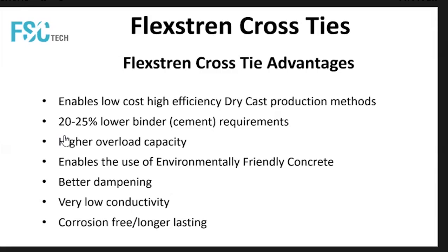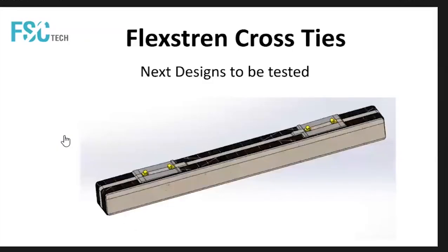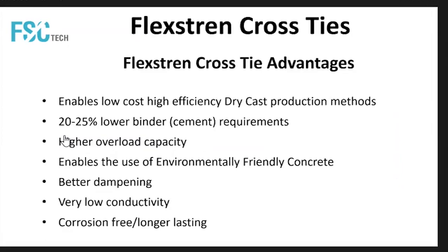You can use environmentally friendly concrete, like I was saying, and you can get better dampening because you can tune everything to a lower level of pre-stressing. First of all, because you have the fiber in the area where you have the maximum tensions, you don't even need that amount of stressing. There is an interesting study done by a Turkish railway showing the dampening of noise at various levels of pre-stressing. When you get to a relatively low pre-stressing level, the dampening increases a lot.